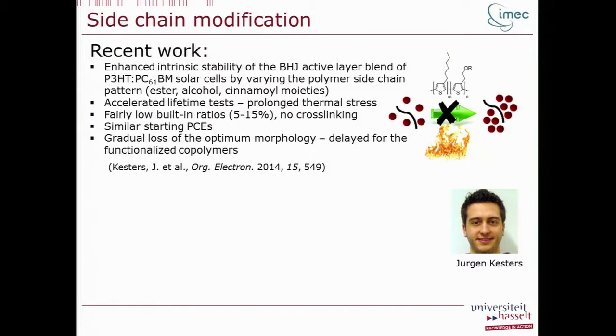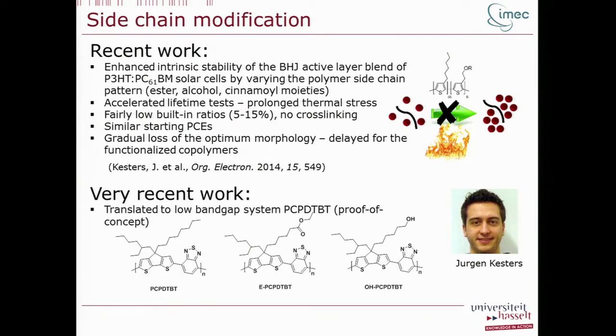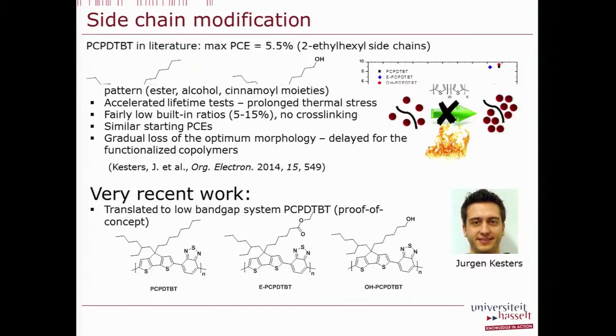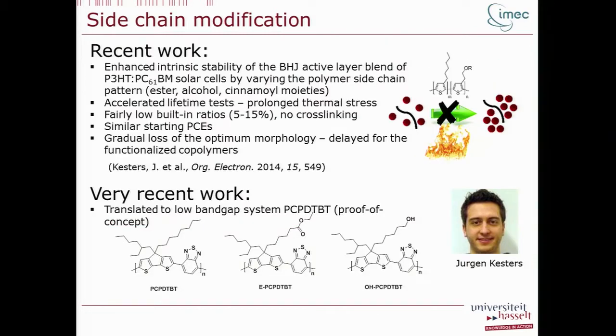This is work being done in the PhD of Jürgen Kesters. So very recently he published in Organic Electronics this introduction of side chains on P3HT materials, and what he's shown that even with bringing in just a small amount of these side chains, 5 to 15%, a dramatic increase of stability was obtained. Very, very recently, he also used this approach to PCPD-TBT. So also there he introduced these sidechains just as a proof of concept.